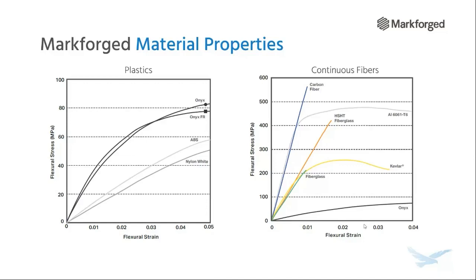It's also important to note how each one of these fibers performs under a flexural load. Take a look at Kevlar, for instance. We see that there's quite a bit of strain before the part actually breaks, and so it's able to absorb a large amount of energy. And then we have the high strength, high temp fiberglass, which in itself almost reaches the maximum strength of aluminum. And then we have aluminum there.